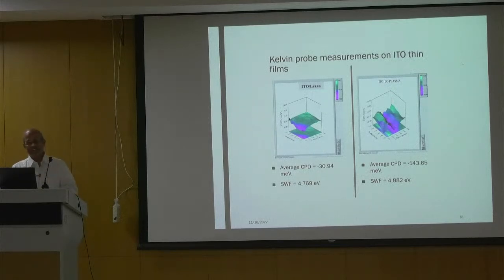So if the properties are different, let us find out how the surface work function is going to change. We have taken a plastic substrate called Lexan and a glass substrate. On both substrates, at the same time, under identical parameters, in the same chamber, we deposited tin doped indium oxide, ITO. Because it was done at the same time, you would expect both thin films of ITO to behave the same whatever the substrate. It's not according to physics, because the substrate has some surface energy that decides how the thin film is formed, which is a topic called nucleation, growth, kinetics and thermodynamics. That is a most complex subject.